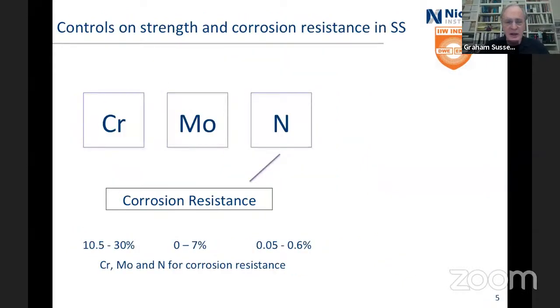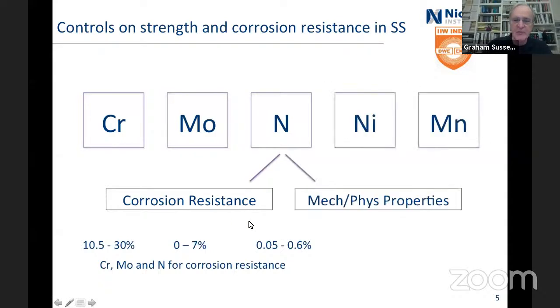So what's actually in there? We've got chromium, we've got molybdenum, we've got nitrogen. Those give you your corrosion resistance. And you've got somewhere between 10.5% and 30% chromium, up to about 7% molybdenum, although there aren't many alloys around, it just makes it a bit hard to weld. And you've got nitrogen, nice, free, easy to put in nitrogen, which does good things for the corrosion resistance.